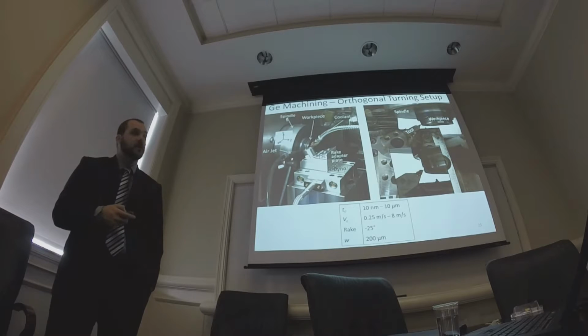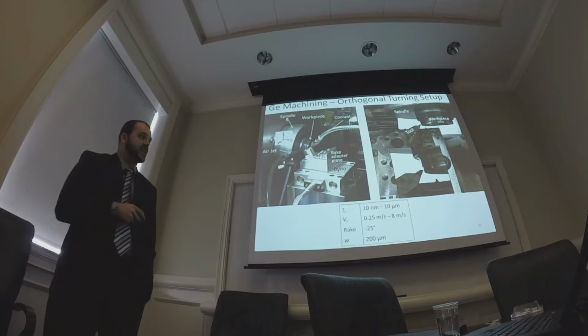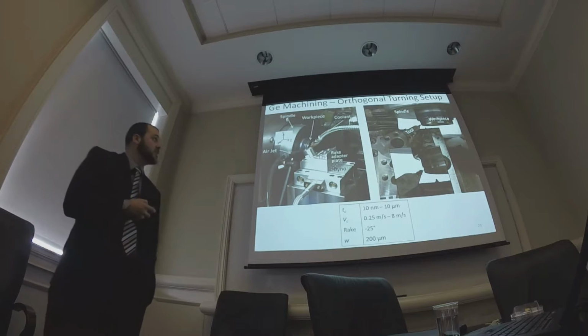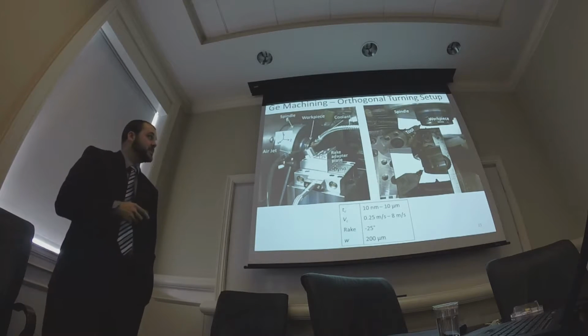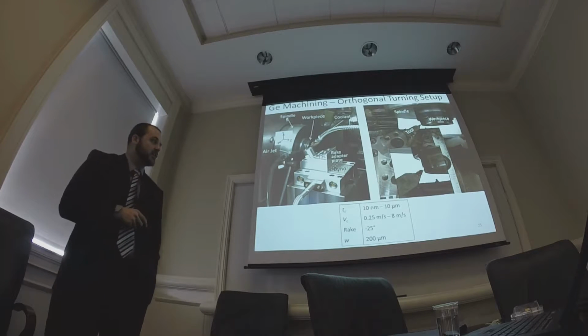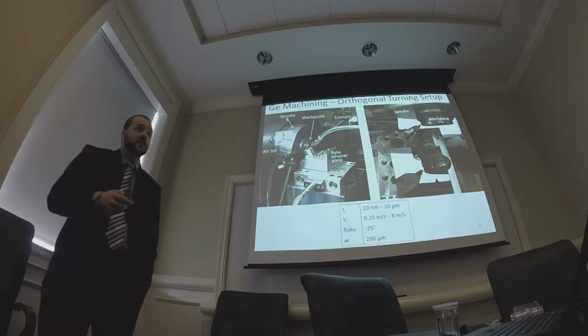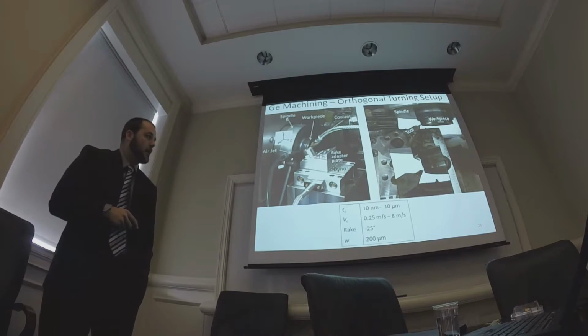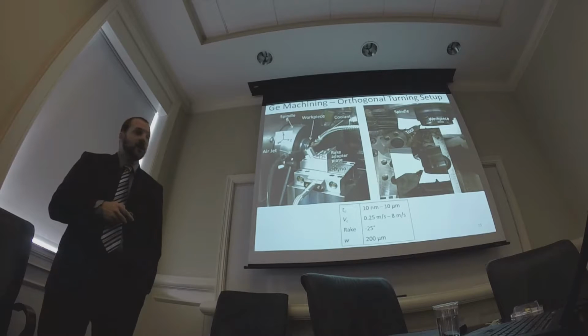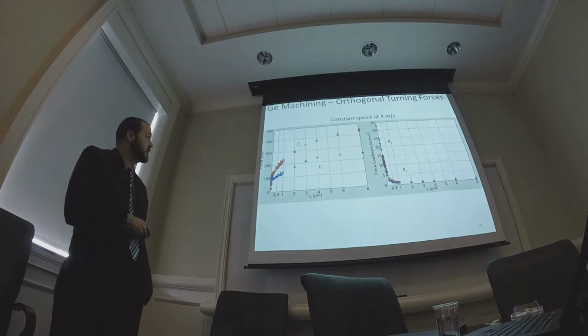So we wanted to simplify the germanium cutting operation, so we went to this orthogonal cut. Same setup as the IRG-26, but I included this adapter plate to induce a negative 25 rake angle. Same size tool, different tool, but same shape as the IRG-26, we just put this negative rake. Now we worked with a slightly wider range of chip thicknesses, went a little smaller, and went through a range of speeds, negative 25 rake and a constant chip width of 200 microns.